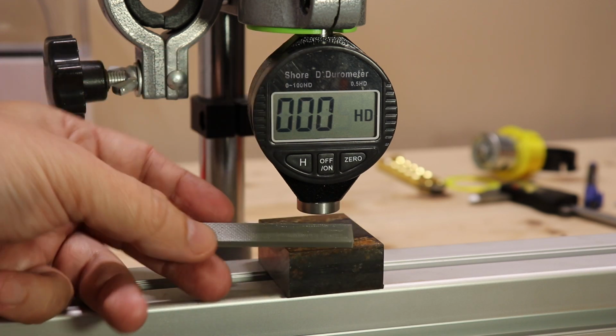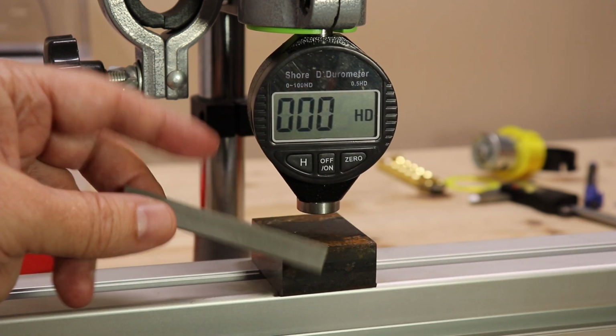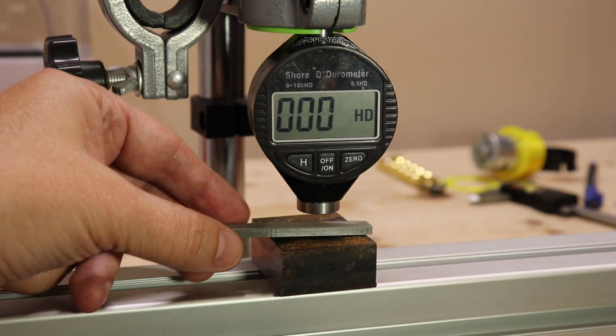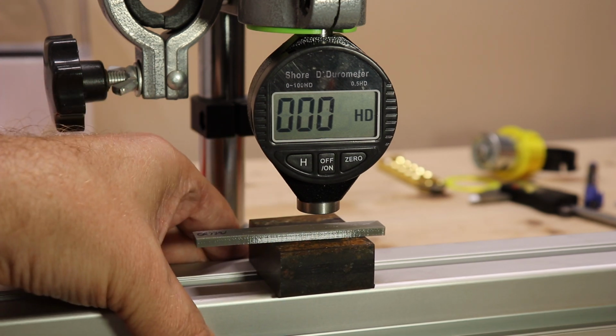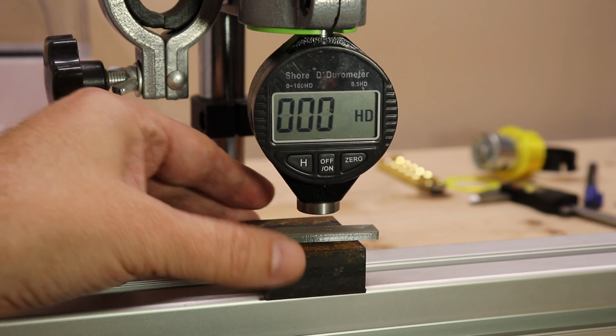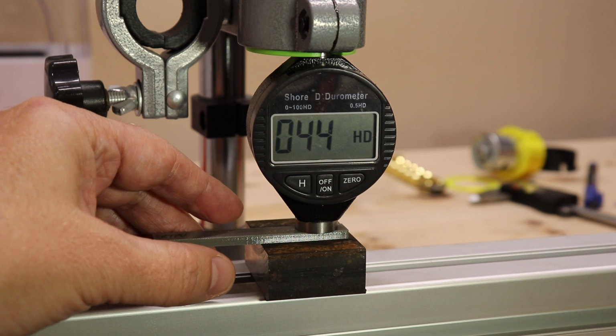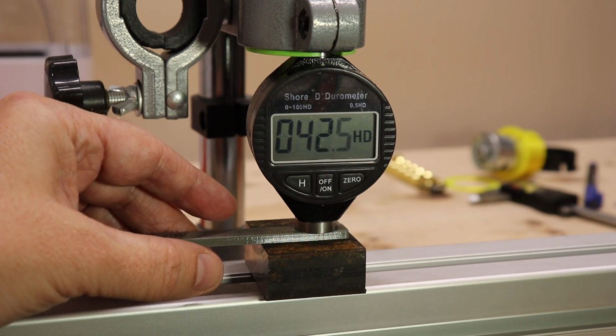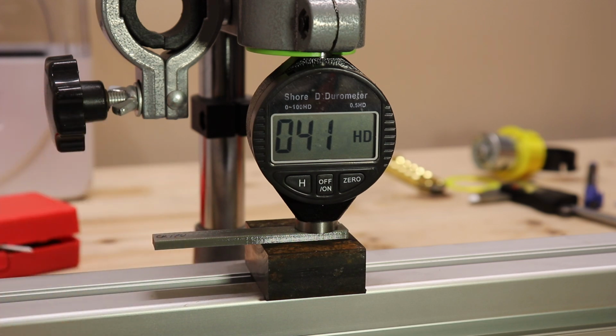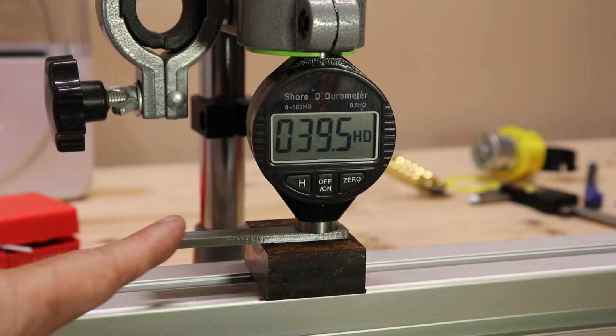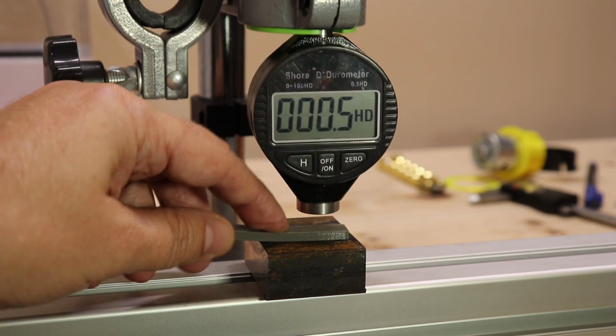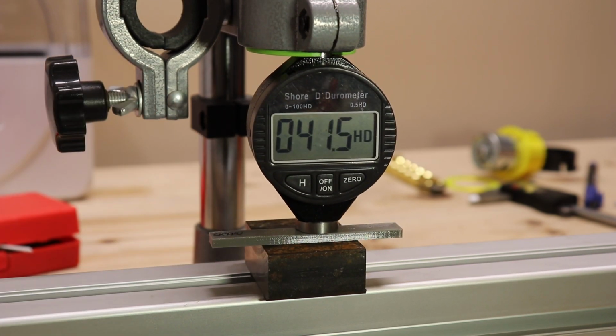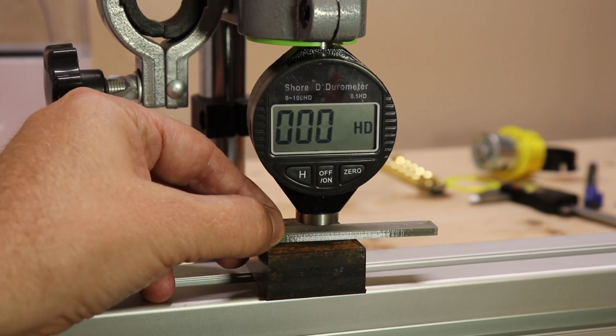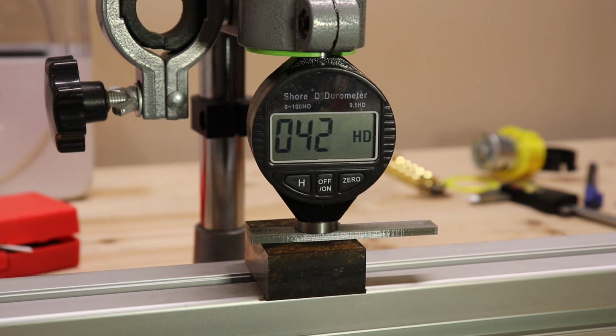And this is Creality TPU, and probably for this I have to replace the Shore type. This is Shore D, but let's try it. Actually I don't know the hardness of this CR TPU. It's not on their website, but if it is approximately 95, then on this scale it should be around 40. So let's see. I have to wait until the penetration stops, and it slows down now. I understand why they recommend a different type of scale for rubber. 39, 40, 41. Okay.